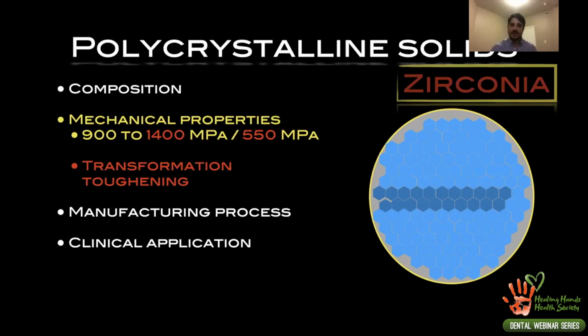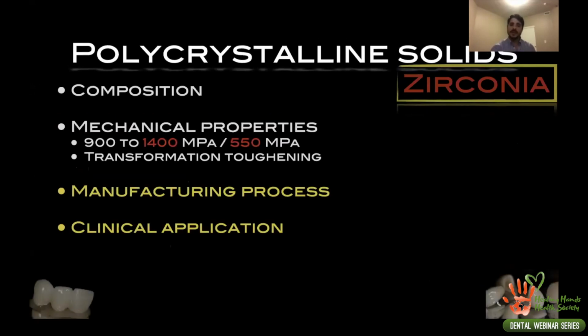So then you ask, okay, now we have the tetragonal phase transitioning to the monoclinic, and that causes the healing of the fracture line. But then why don't we have that with the translucent zirconia? And the answer is, again, remember that the translucent zirconia is stable in the cubic phase, not the tetragonal one. Because of that, the cubic cannot transform into the tetragonal, and then it cannot transform into the monoclinic. For that reason, you don't have transformation toughening happening with the translucent zirconia. So that explains why the translucent zirconia is 1/3 of the strength of the conventional one.